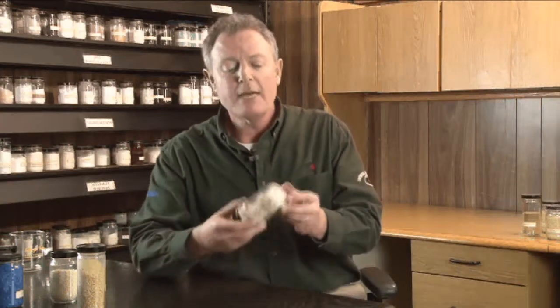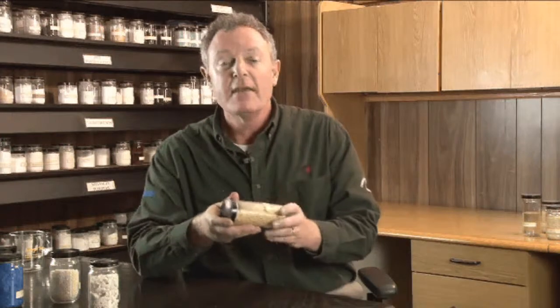And so what we did with the Rollo-Mixer is we played around with different aspects and adapting the machine to this product, and we ended up with a finished product where they come out of the Rollo-Mixer and they go directly into an extruder to make these pellets. And when they went to measure the ash content after processing this material in the Rollo-Mixer, they found that the range between these pellets was between 12.5% and 13.5%, not 6 and 20% as before. So they tremendously improved the quality of these thermoplastic elastomers, which is also referred to as a TPE.